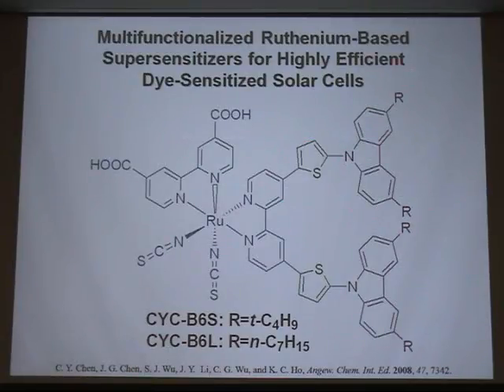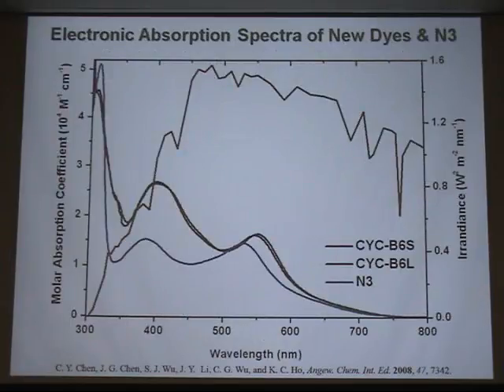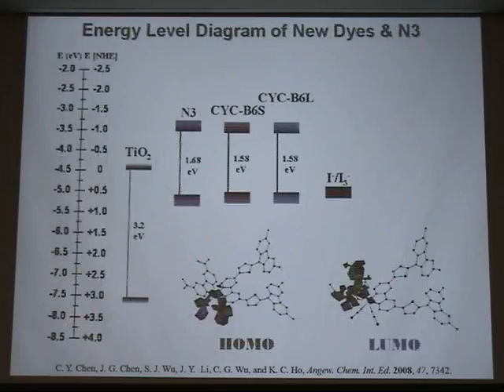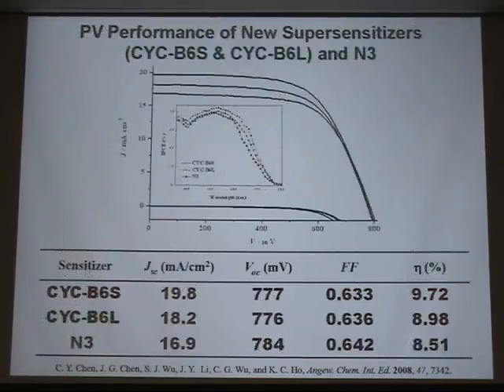Now, here you have a bipyridine, thiophene, and carbazole system. And here you have a short chain. Here you have a longer alkyl group, a long chain. And we want to compare this. And you can see, compared to N3, both, whether long or short, also get higher absorption coefficients. And there's not much difference in terms of band gap, HOMO-LUMO, but the cell performance improved with a very short chain.